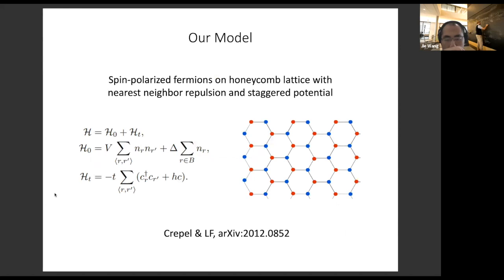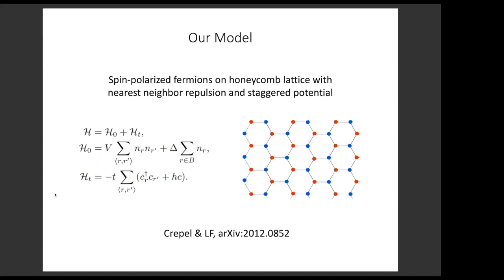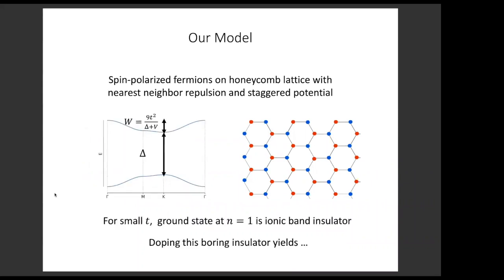So let me start with a concrete example to illustrate this general idea. Let's consider this toy model of fermions on a honeycomb lattice. The two sublattices A and B have a different on-site energy. The sublattice potential difference we call delta, and there's nearest neighbor hopping t, and then there's nearest neighbor repulsion V. Later we're going to generalize this model to the spinful case and to the case with longer range interactions. Next slide.